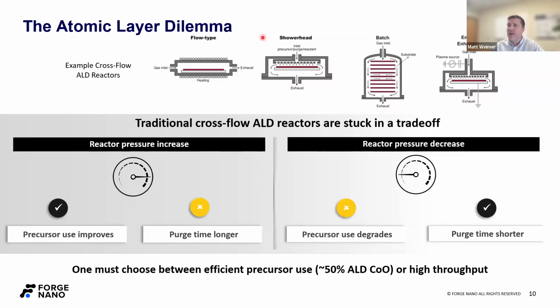So in all of these orientations, you have to choose a pressure regime to work in. So if you choose a high pressure regime, your precursor molecules are moving more slowly, which means they have time to travel around the reactor, diffuse out of their laminar flow lines to give you a uniform film thickness across the wafer. But because those molecules are moving slower, it takes longer to purge. As I mentioned before, that's the big slow step in ALD. There's also this horrible relationship where the more precursor you put in, the longer it takes to purge, and therefore the slower your ALD process is.